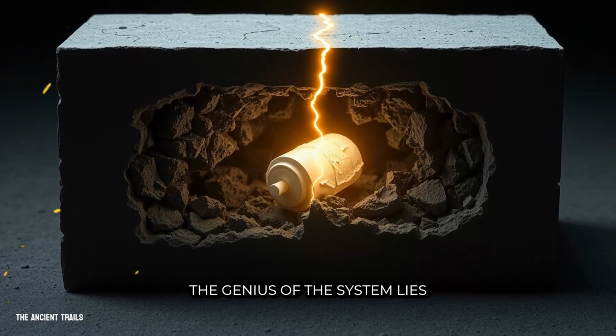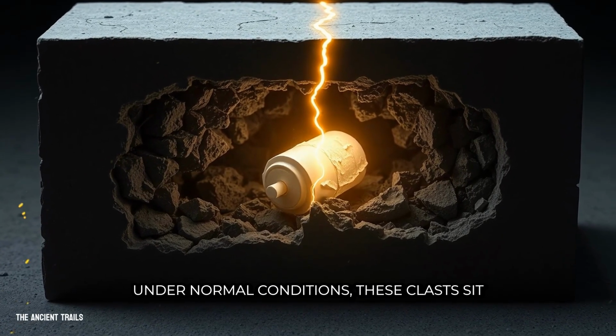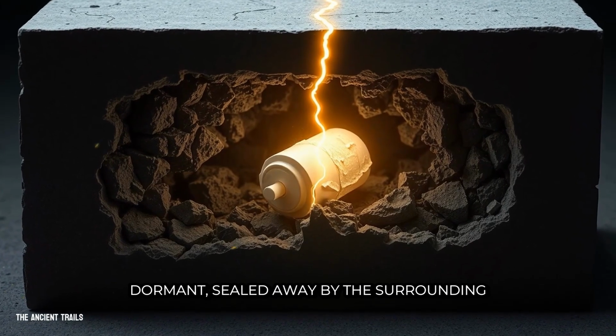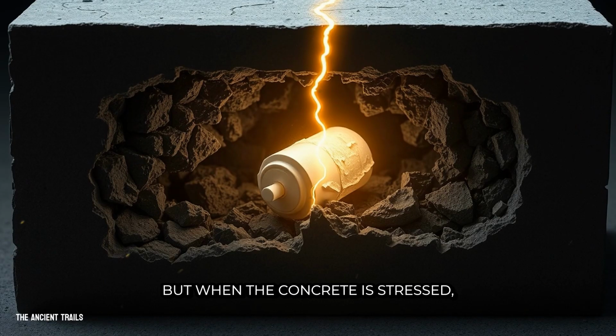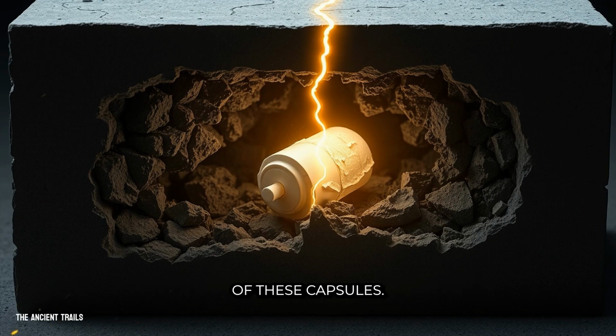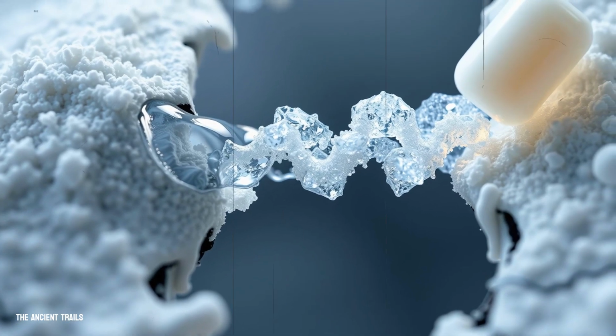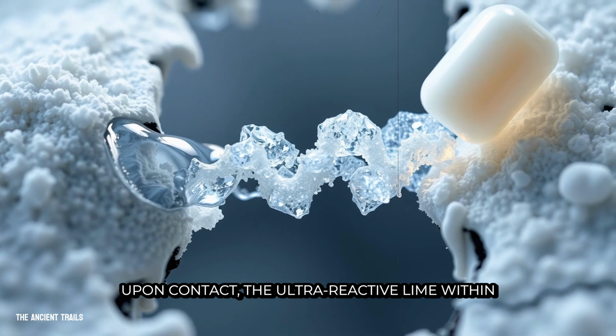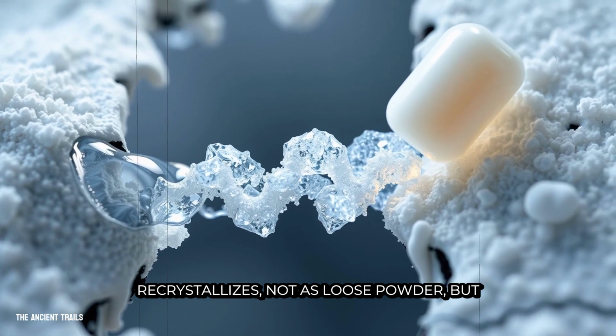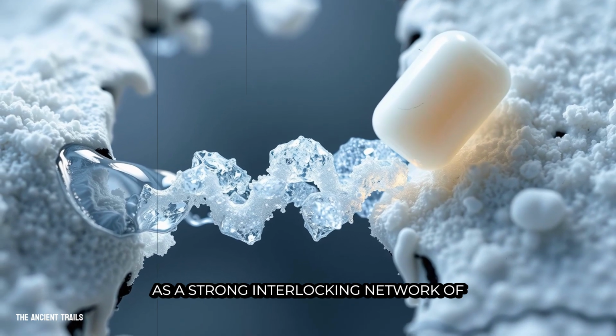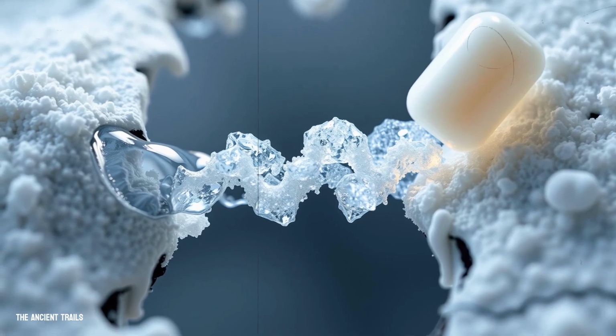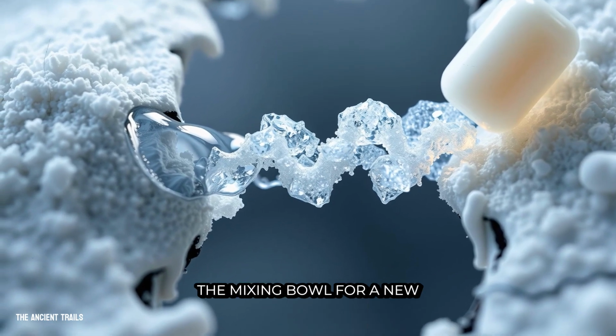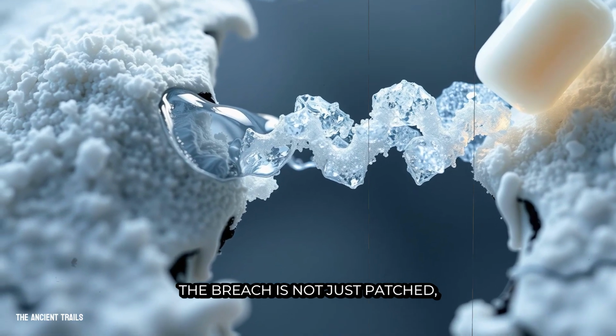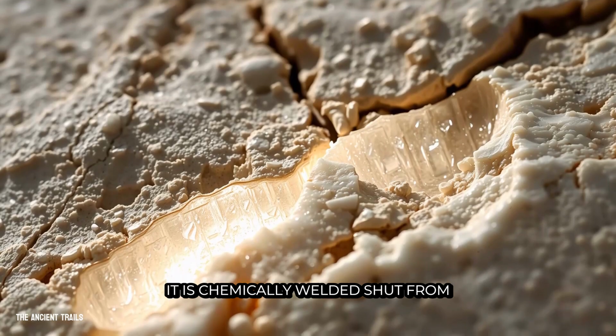The genius of the system lies in its trigger. Under normal conditions, these clasts sit dormant, sealed away by the surrounding crystalline armor. But when the concrete is stressed, when the tiniest hairline crack begins to propagate, it eventually intersects one of these capsules. Water, whether from rain or seawater, seeps into the newly opened fissure. Upon contact, the ultra-reactive lime within the clast dissolves and then rapidly recrystallizes, not as loose powder, but as a strong, interlocking network of calcium carbonate. In essence, the crack itself becomes the mixing bowl for a new batch of cement. The breach is not just patched, it is chemically welded shut from the inside.